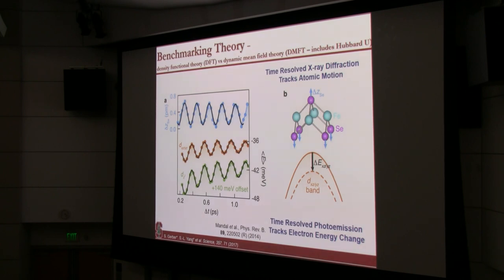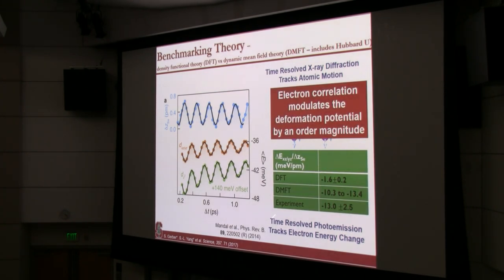In this sense, it's a highly constrained experiment because the typical material has a lattice constant of a few angstrom. You don't want to change the lattice constant by more than a percent of the intrinsic material, because you may well study something else if you deform it too much. So it's intrinsically a very small amount of change, but you can clearly see that. And of course, you need to do all the fluence dependence, make sure you're in a linear response regime and all that. So I'm not going to go into the detail, but a good thing about it is that